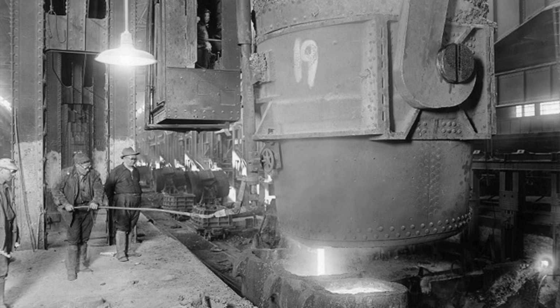German metallurgists had achieved something American steelmakers dismissed as impossible. They had created armor plate that provided protection equivalent to steel 50% thicker through a process called face hardening. The principle was theoretically simple but practically complex. Rather than making the entire armor plate uniformly hard, German manufacturers created a dual-layer structure. The outer face of the plate, the side facing enemy fire, was heat-treated to extreme hardness, approaching that of tool steel. This surface layer, typically 20 to 30% of the plate's total thickness, would shatter incoming armor-piercing projectiles on impact.